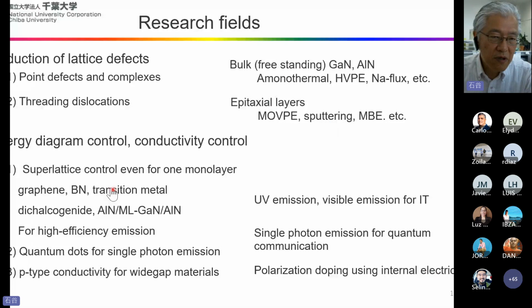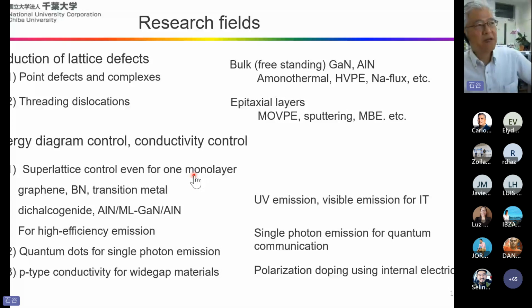And on the basis of this crystal technology, energy diagram control and conductivity control will be conducted. And in this case, superlattice control, even for one monolayer, is now researched. For example, I think there are many milestones for the practical fabrication of graphene, boron nitride and transition metal dichalcogenides. But in contrast, aluminum nitride, one monolayer gallium nitride, aluminum nitride, this kind of structure is based on the crystals we can utilize at present. So these studies are also conducted, but a very high level of crystal quality is required.